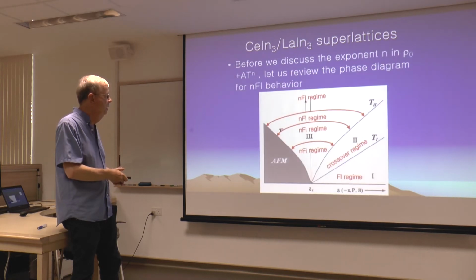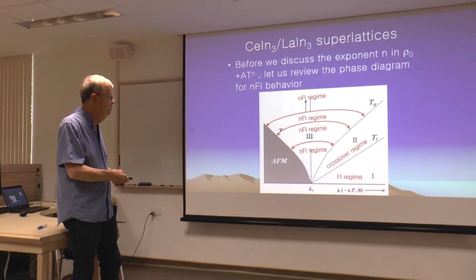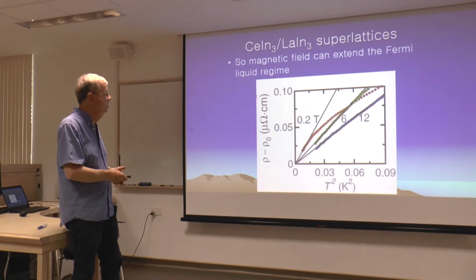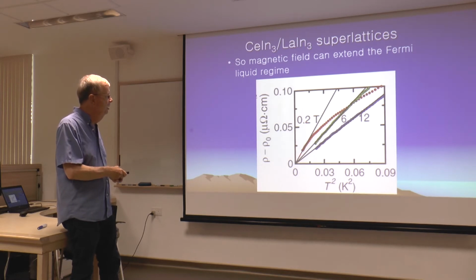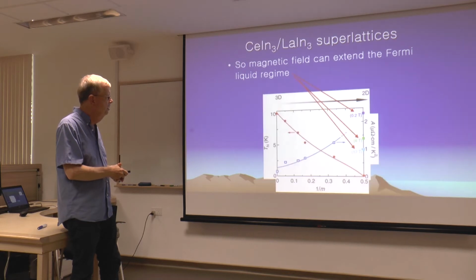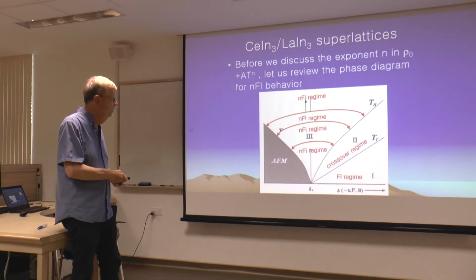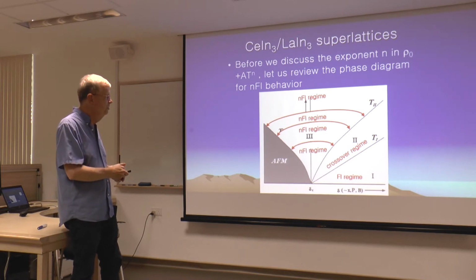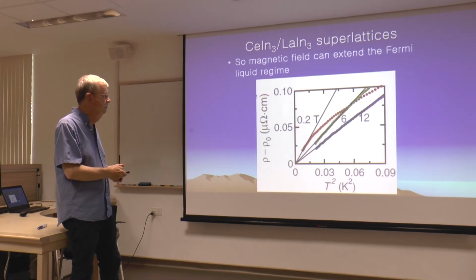So again, if I go over here to 6 Tesla, I can get T squared for some region, and if I go over here to 12 Tesla, I can get T squared for some further region. And so that's what this is. Here is the little bit of field where I got a little bit of T squared, and then it went away because in this diagram it goes over to the crossover regime. So here's Fermi liquid. I told you this was hard, especially since they keep going back and forth.